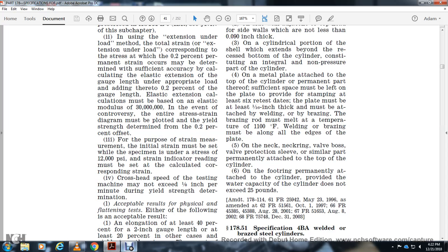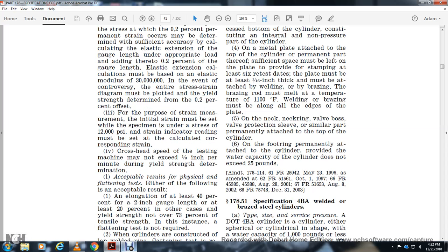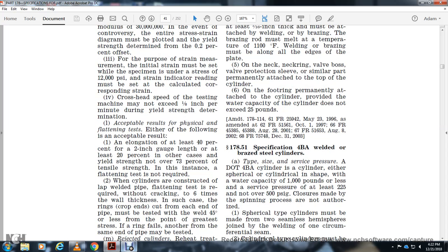Acceptable results of the physical and flattening test are either of the following: elongation of at least 40% of the 2-inch gauge length, or at least 20% in the other case, with the yield strength not over 73% of the tensile strength. In this instance the flattening test is not required with the cylinders. For constructed welded pipe, flattening tests are required without cracking at 6 times the wall thickness, and in such case of the rings cut from the ends of the pipe, the weld must be tested at 30 and 45 degrees from the point of the greatest stress of the ring.